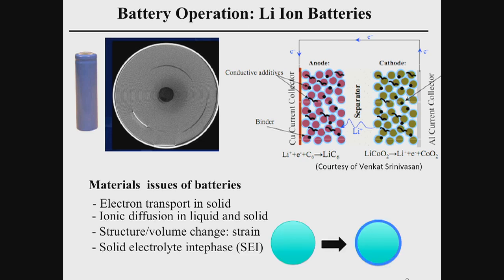And the fourth thing you need is, on each of these particle surfaces, they are soaking in electrolyte for 3 years. Imagine you sit in water for 3 years, what happens? Well, you get corroded away, right? So the only reason this particle can survive is it has a passivation layer. It reacts with this organic electrolyte a little bit, forming a very thin coating, let's say 20 nanometers to 100 nanometers, that will protect this particle from further corrosion.